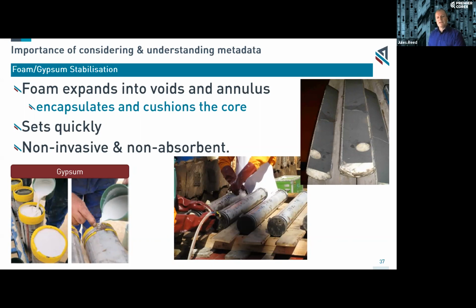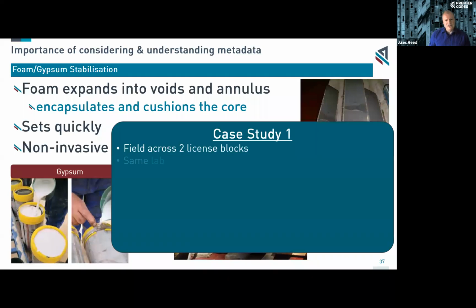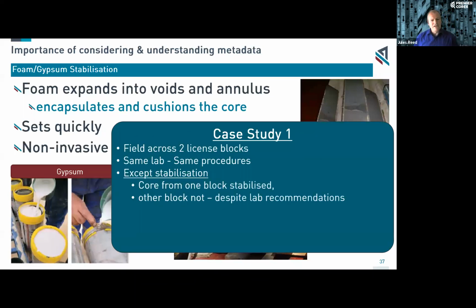At the well site, as the core comes to the surface, the core is stabilized. So either by gypsum or by foam injection, we put this surrounding the core and stop it from moving. Now this particular core was unconsolidated, and so what the stabilization was doing was stopping the unconsolidated core slumping and moving and changing properties.